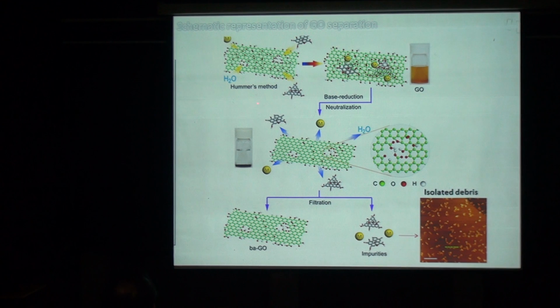So what we do is this. We synthesize the graphene oxide by the usual Hummers method, and it produces graphene oxide with all kinds of functional groups. The question is, which one is responsible for the catalysis? How do we know which one is useful? Maybe some is useless. Now, what we do is we do a base reduction. It happens that during the oxidative treatment of graphene oxide, you actually generate a lot of small fragments. It's oxidative debris, small fragments. This oxidative debris is super hydrophilic, has a lot of oxygen functional groups.